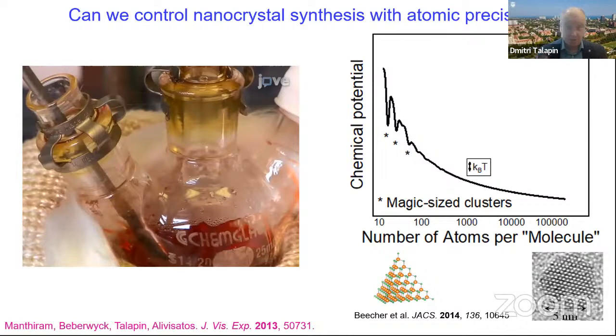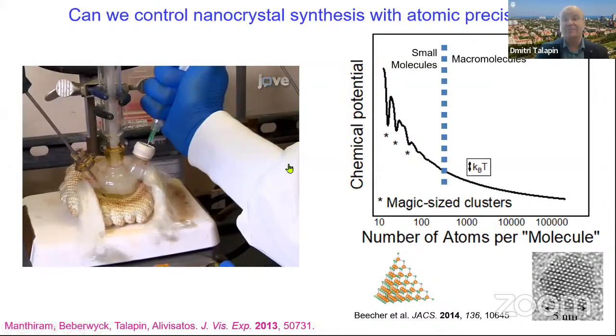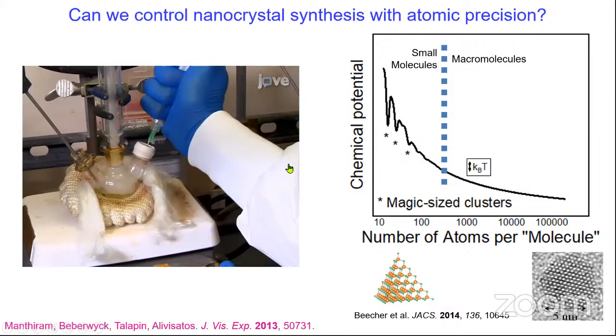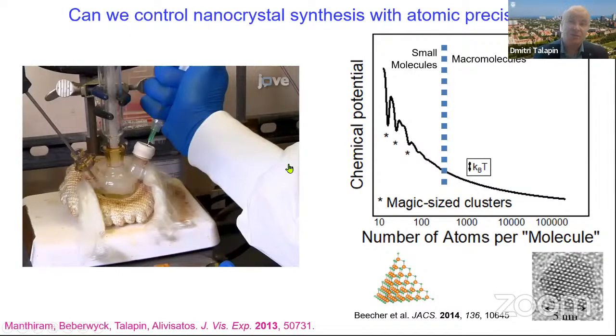First, our molecular precursors react and go through a very complex nucleation process. After we nucleate a new phase, and this new phase can be a metal, a semiconductor, a magnetic material, it evolves by adding molecular units to the growing crystal and just keeps increasing in size. At some point, when we have very small molecules, we can isolate small crystals, we call them clusters, with true atomic precision. But when we move past a certain size, typically hundreds of atoms, we lose the ability to control this matter with atomic precision. Just adding or removing a structural unit does not change the free energy or chemical potential, and we cannot use thermodynamics to do it. Pretty much the same problem as with polymers.